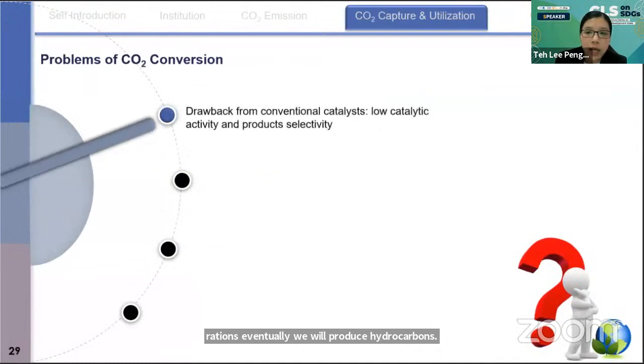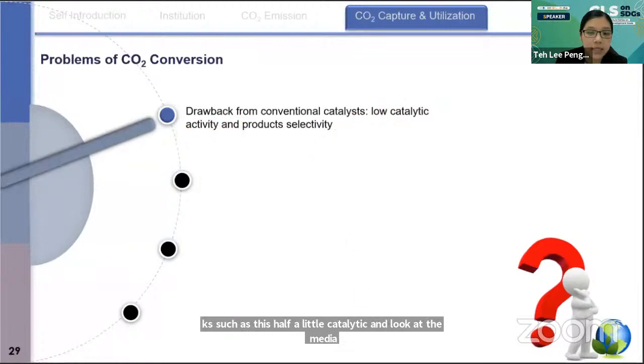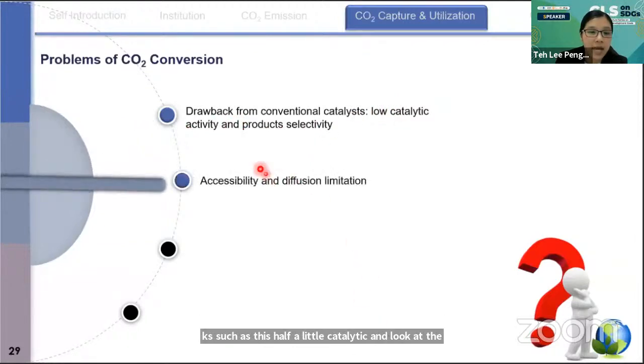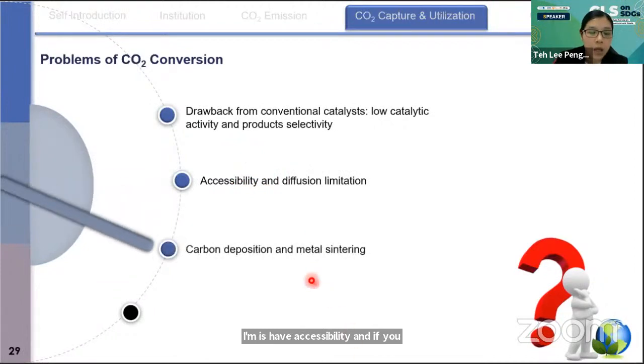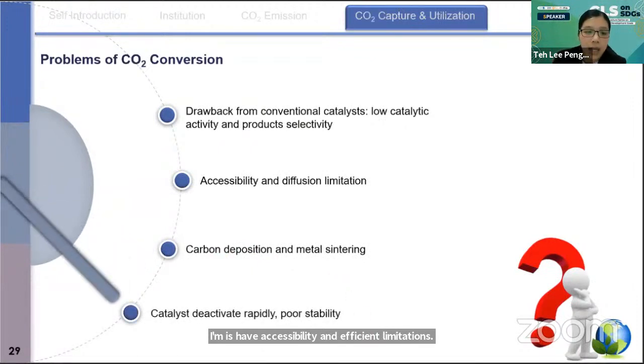To conclude, the existing catalysts possess several drawbacks, such as low catalytic activity and low product selectivity. They have accessibility and diffusion limitations. They will have carbon deposition and metal sintering, and they will deactivate rapidly and have poor stability.